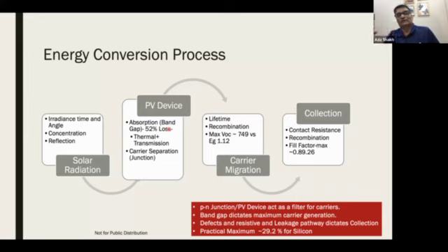Also, whenever you do the processing, you create defects. So the recombination becomes very critical. The lifetime is also dominated by the quality of silicon. Like we talked about, float zone being highest quality, multi-crystal being lower quality, and Czochralski somewhere in between. So that plays a role as well, and there has been a tremendous progress. So you have to look at radiation.